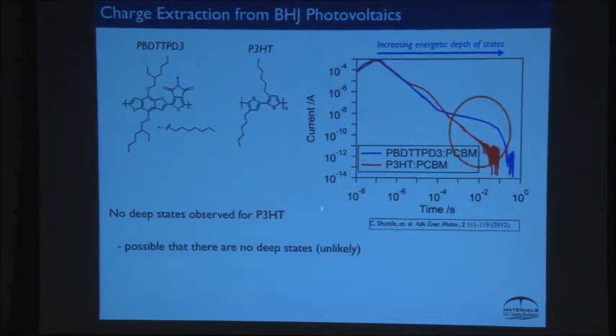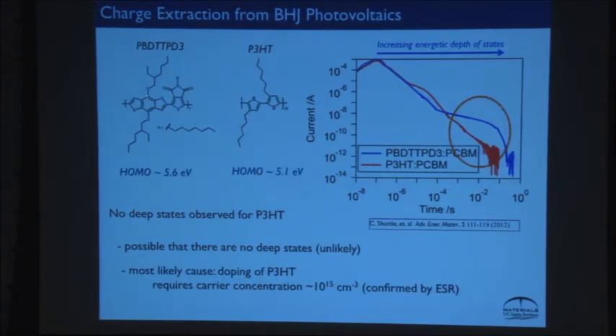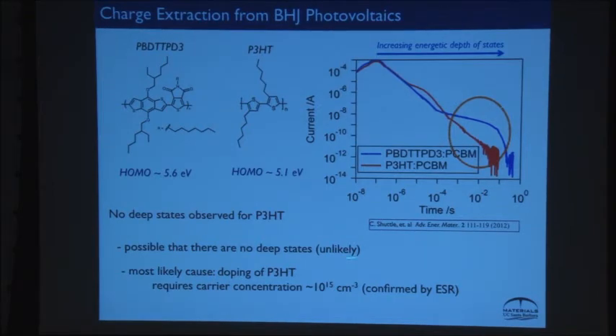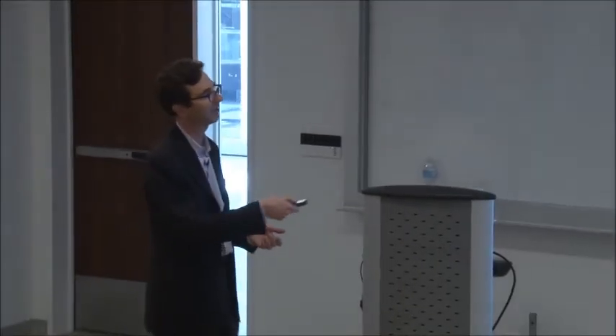And it's possible there aren't any deep states in this, but we didn't think that was likely because we did that photodoping here and we could get rid of them. Well, it turns out one thing that people don't keep track of is that these materials are sometimes a little lightly doped. And you can measure using ESR how many dopants there are, and it's something like 10 to the 15th. And that's exactly how many states it takes to wipe that out. And so what these studies are telling us is that this is something you do in conventional semiconductor physics, but it's not done routinely here, and it really impacts how you think about the transport measurements in these systems.